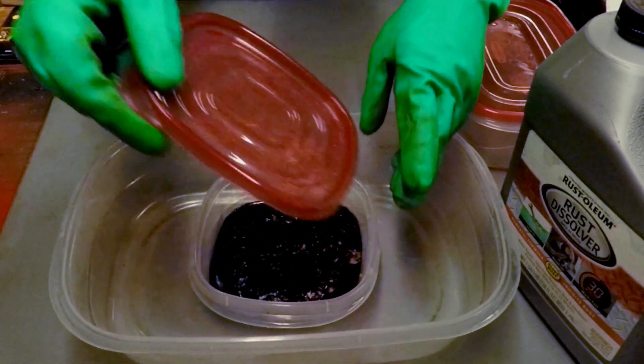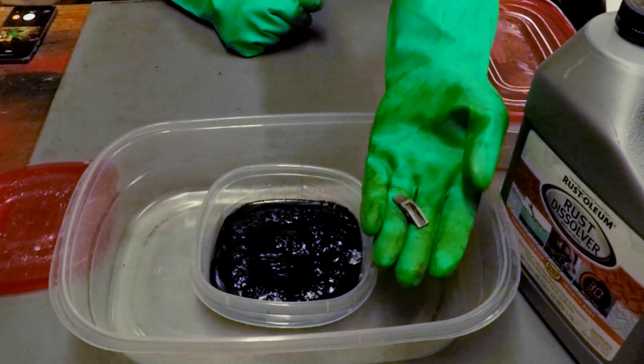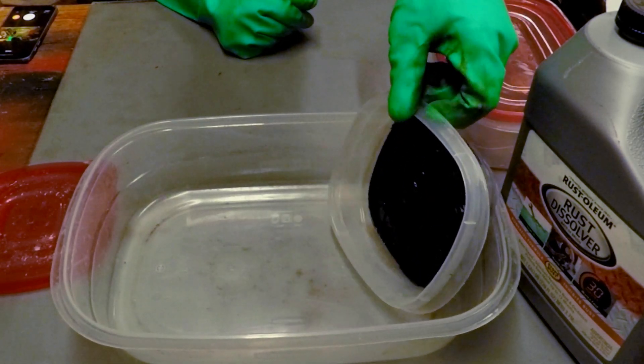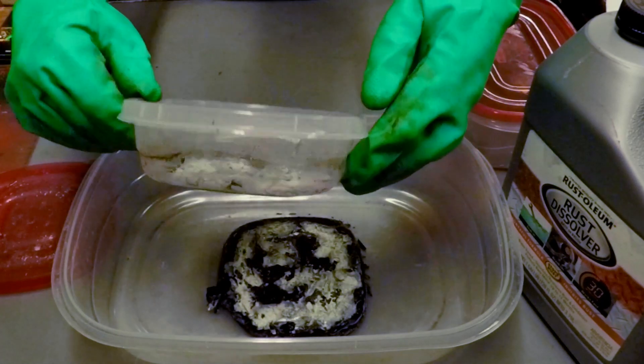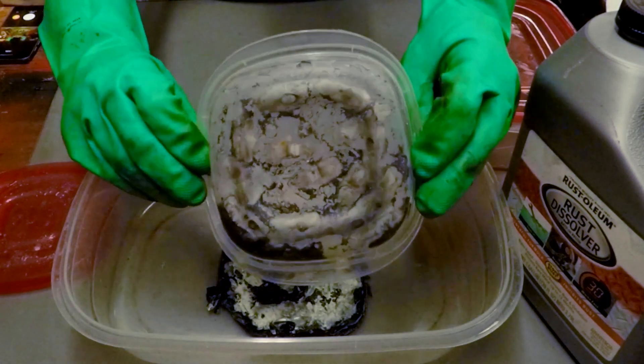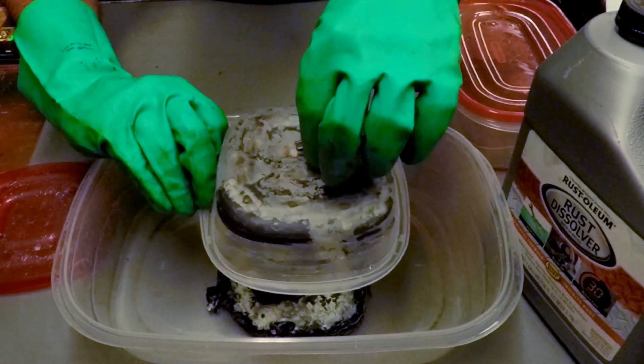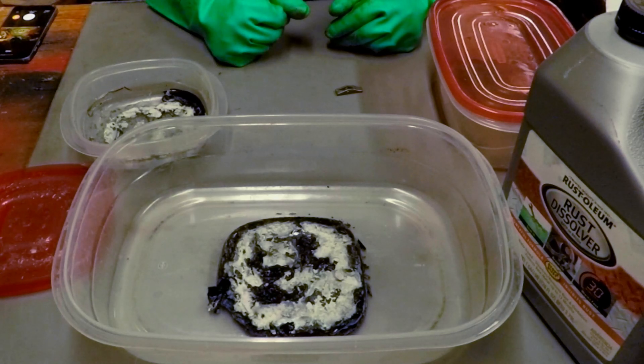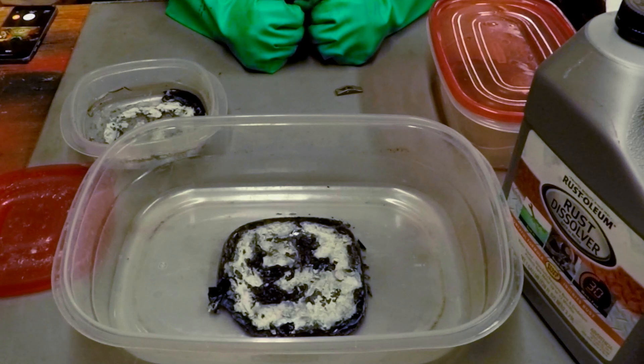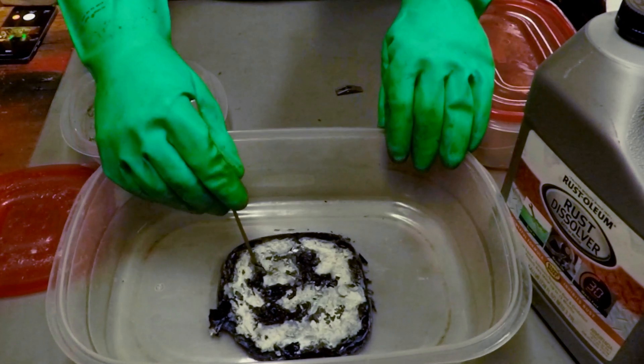And that's what you get — there are 14 of these in there in the Evapo-Rust. I no longer have any parts at all. You can see the outlines of the little parts, you can see where they were resting on the bottom. I've learned about a hundred and forty dollar lesson here: do not soak this stuff in Evapo-Rust anymore if you're using metal injection molded parts — keep those free of this stuff.